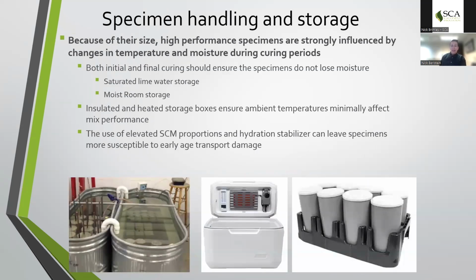As I mentioned as well earlier, these specimens tend to be much more susceptible to abuse on handling and storage conditions. Determining how cylinders are going to be stored, what the expectation is for storage and transport are all very important. Oftentimes something as simple as getting a rack for your specimens during transport can make a world of difference. If the specimens are weaker at that early age strength, bouncing around in the back of a pickup truck is not a good way to demonstrate that your mix design is in fact a good mix design. So again, just having those conversations, especially with testing labs, who can often be a bit more removed from initial stakeholder conversations, can really help eliminate any potential issues, especially if there are issues that might not actually exist in the element itself.